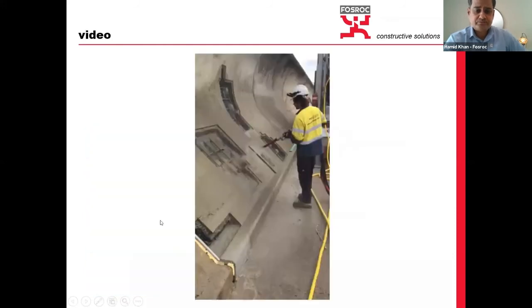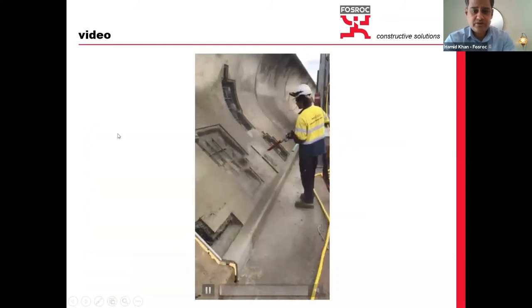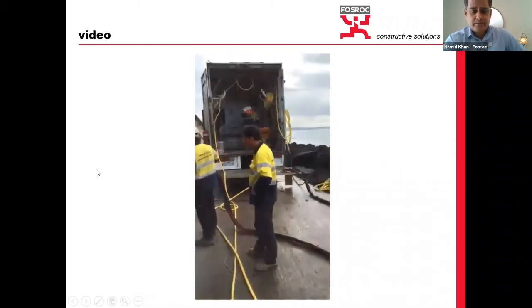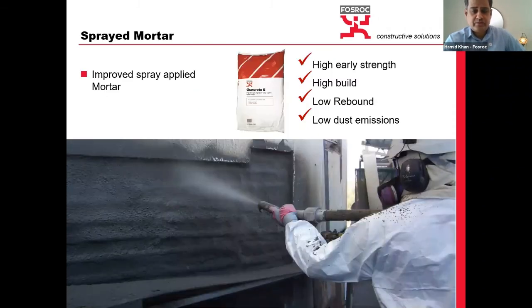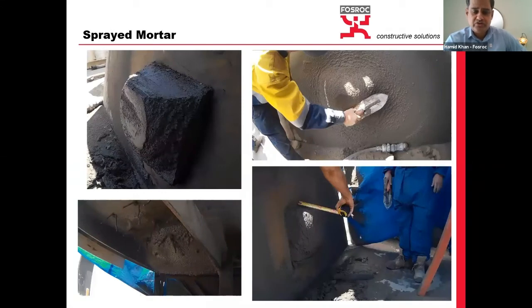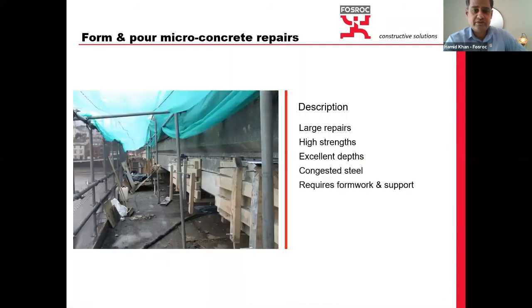So this is, I think, let me see if it works here. Yeah. So this is a good surface preparation. These are excellent surface preparations. You can see an excellent saw cut at the edges, which would definitely improve the bond strength. The sprayed mortars these days can go very high, up to 150 millimeter. This is dry spray mortar in one go, 150 millimeter. Vertical and overhead may be a bit lower, but sprayed-on systems are really good repair mortars, and they're very durable as well. Excellent for larger areas.